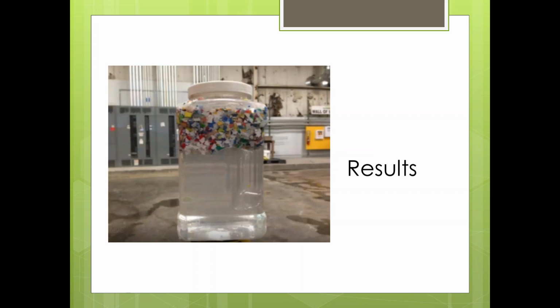After the wash bath happens, they'll actually compress them and squeeze out a bunch of moisture. They'll run them through a series of dryers and batches. And really, this is what the wash bath is trying to accomplish. It's trying to separate out things that are lighter than water, aka plastics, from things that are not. If we have a very good wash bath stream, we sample it on a very routine basis every shift. This is the type of content that we'll pull directly out of our wash bath, just to test and see what kind of quality we're getting from a washing standpoint as well.